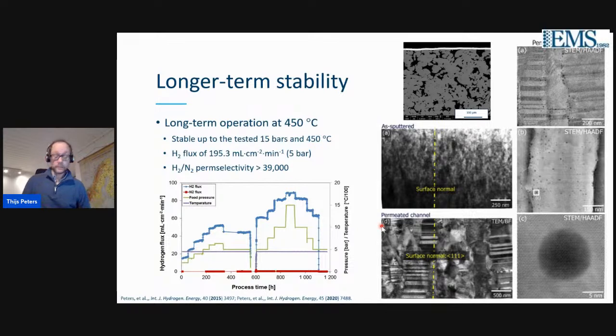Also the longer term stability. Basically what happens when you operate palladium membranes at a very high temperature is that you get grain growth. And we saw that depending on the temperature, but also on the flux that is being generated, you can either operate the membrane in a very stable manner, but if you stretch it too much in terms of temperature, you get pinhole formation. By post-process characterization of the membrane, we saw that hydrogen cavities were formed along the grains that over time grew together, and then pinholes were formed. This can also be prevented by proper alloying of the membrane.